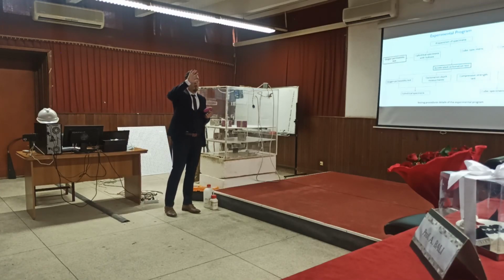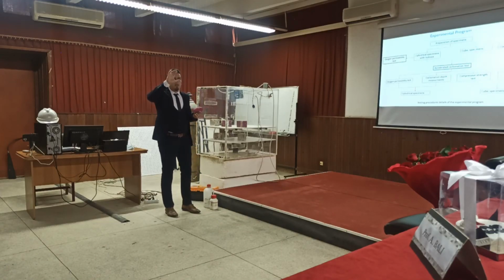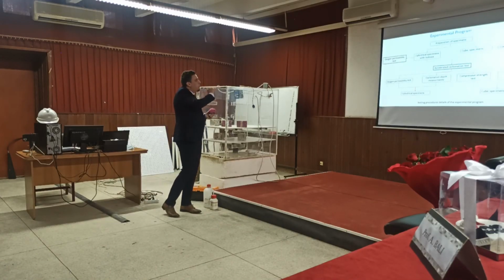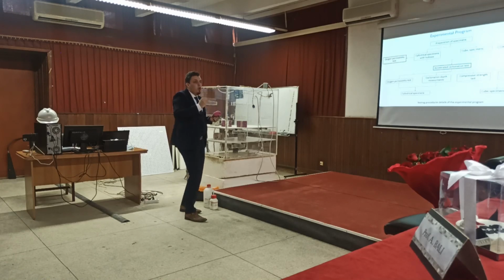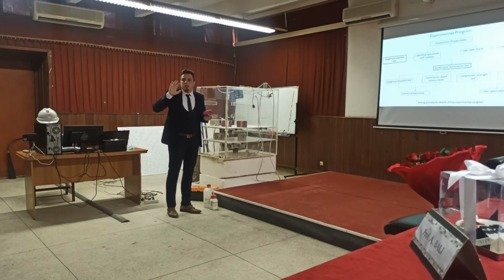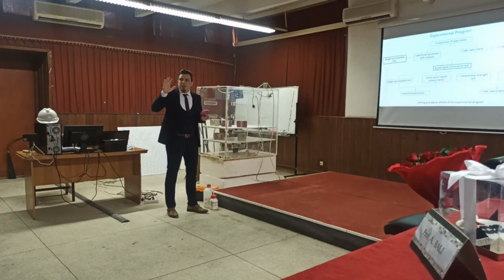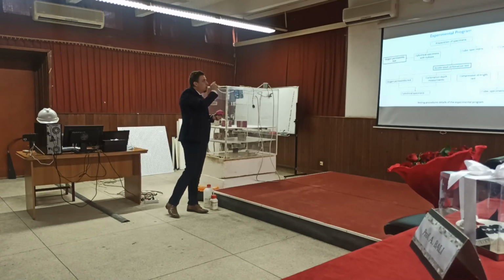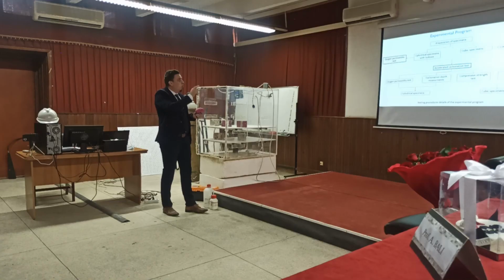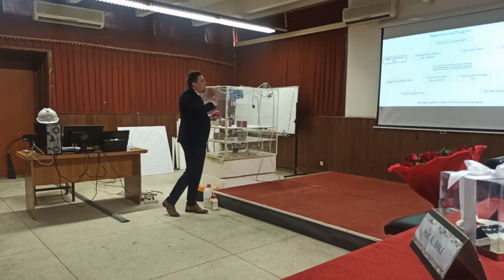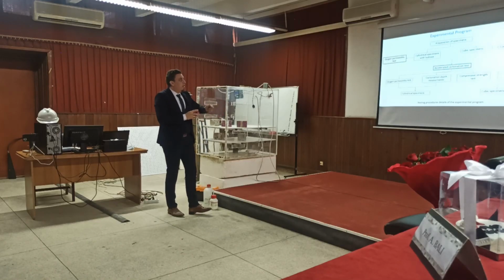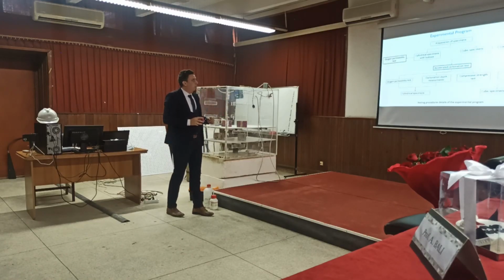Our experimental program is divided into stages. The first stage is to assess some characteristics, the oxygen permeability and the compressive strength, on non-carbonated specimens. After that, all the specimens will be subjected to the accelerated carbonation test. We will assess oxygen permeability, compressive strength, and weight variation again, besides the carbonation depth measurements.